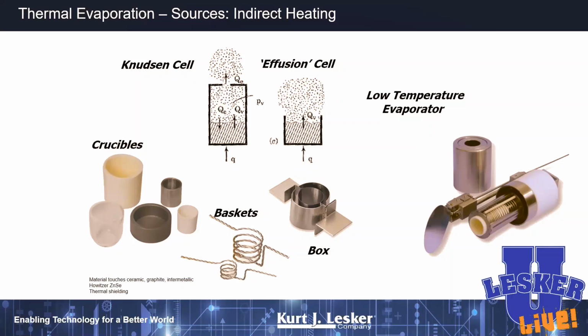Now, if you want to try to make organic thin films, thin films from materials that vaporize at relatively low temperatures, like 100 C, you can use these really nice low temperature evaporation guns here. You can see here that it's got an aluminum oxide crucible, but it's got heater coils all through here. And notice that the distance between the heater wires gets smaller and smaller as we get up toward the mouth of the gun. That's so we can have a temperature differential across the height of the gun, so that we don't redeposit material here at the mouth.